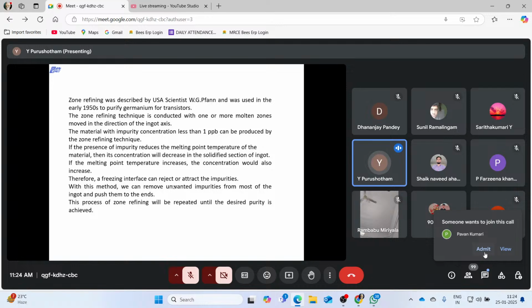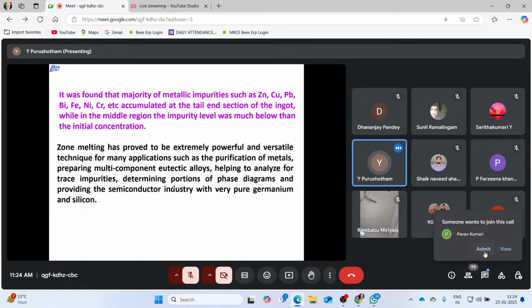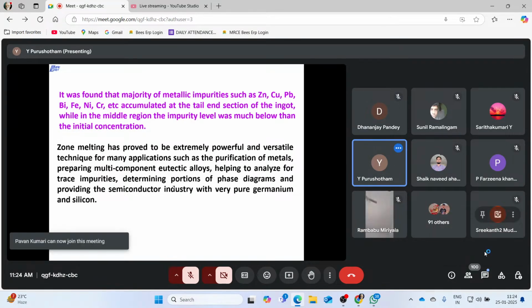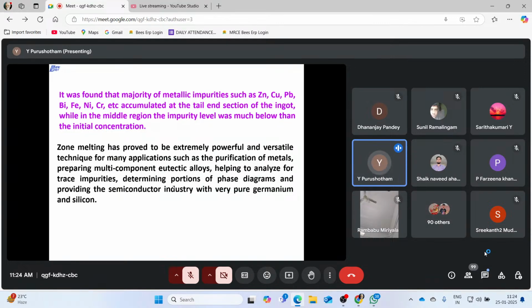But with this, it was found that the majority of metallic impurities like zinc, copper, lead, bismuth, iron, nickel, chromium, etc. accumulated at the tail end section of the ingot, while in the middle region the impurity level was much below the initial concentration. That is what I am telling. So you have to cut it, the middle portion will be of high purity, then you make the two ends a uniform melt again and do zone refining again.